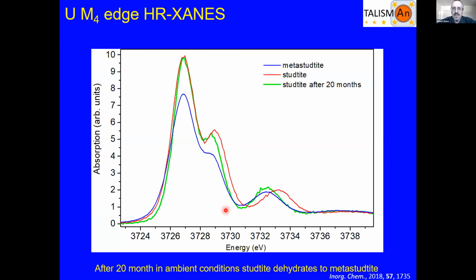If we leave studtite in a cupboard in the beamline for a while and then come back to it after 20 months, we can see that the studtite actually dehydrates to metastudtite. And this fits with some of the thermochemical data that was reported previously, where metastudtite is actually more thermodynamically stable than studtite.